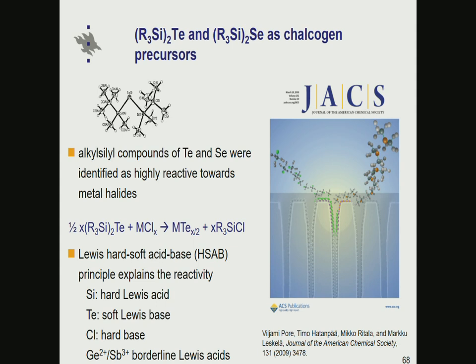We started from tellurium because that was the main focus, but the same works with selenium compounds. And it turned out that they react quite generally with metal chloride compounds. Not only germanium and antimony, but many other metal chlorides reacted with these as well. This is a nice demonstration of a basic chemistry concept, the Lewis hard-soft acid-base principle, which explains the reactivity. In this concept, one divides elements into hard and soft, either acids or bases, and the principle relies on the fact that hard-hard and soft-soft combinations are much better than hard-soft combinations.